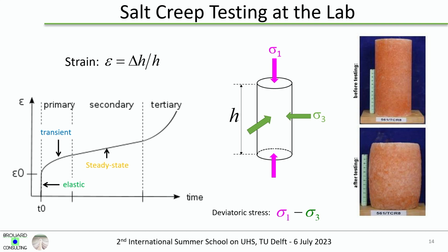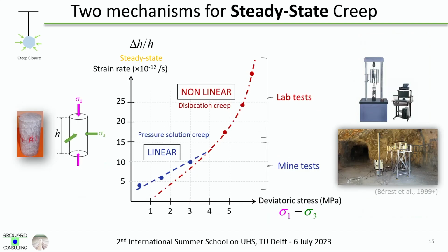Let's just focus on the second part, what we call steady state creep or secondary creep. In fact, there are two different mechanisms for this steady state creep. The most famous is a nonlinear part. This is what used to be measured at the lab. You just measure the strain as a function of time, and you calculate the strain rate, and you have something which is nonlinear. The problem is that you can only make a measurement for a deviatoric stress which is larger, let's say 4, 5 MPa, not less.